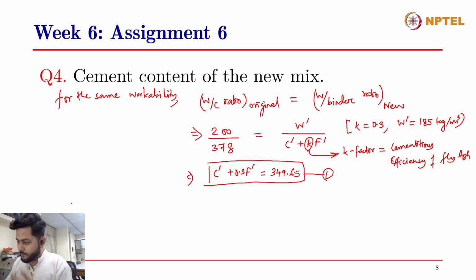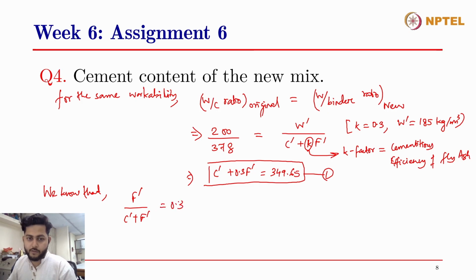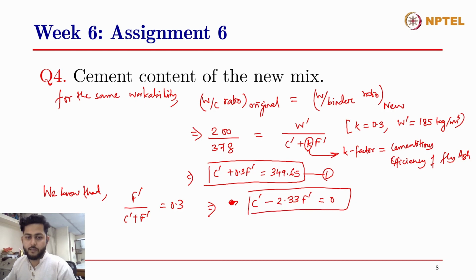And we know that F dash divided by C dash plus F dash equals 0.3, 30% fly ash replacement in the total cementitious materials content. And from there we'll get another equation, which is, and just directly write it out here, C dash minus 2.33 times F dash equals 0. So that will be your second equation.